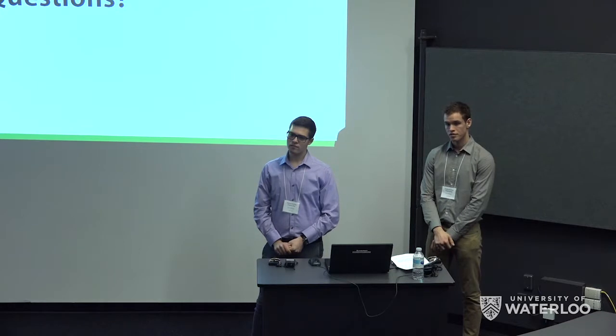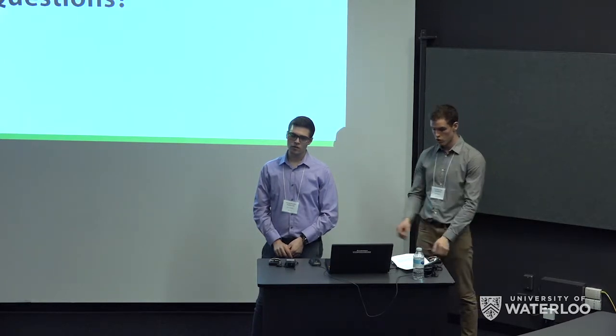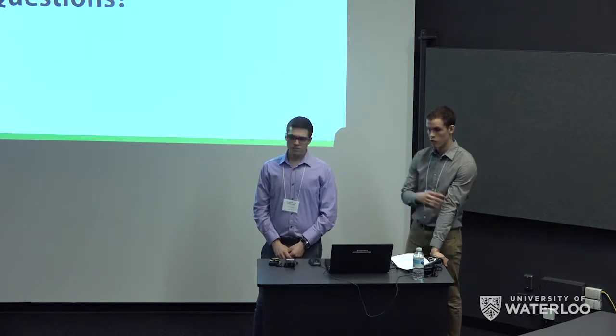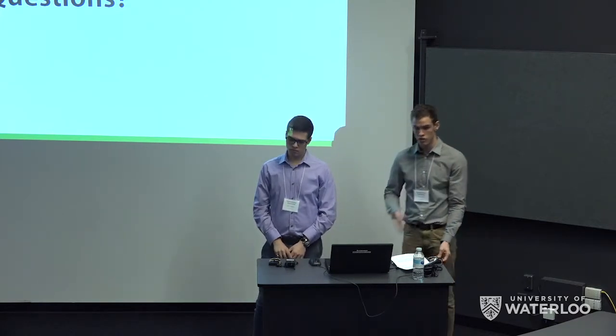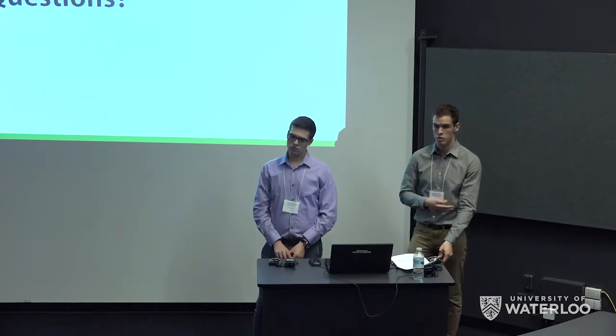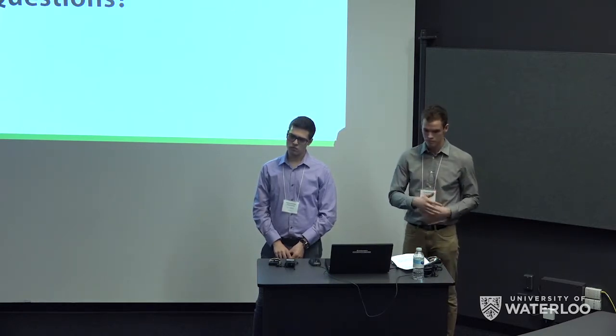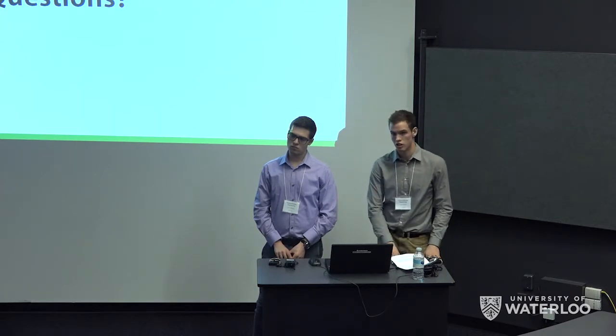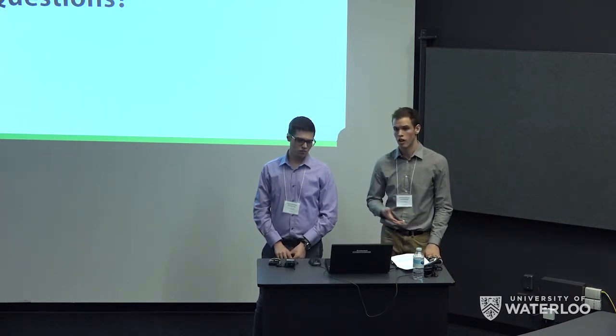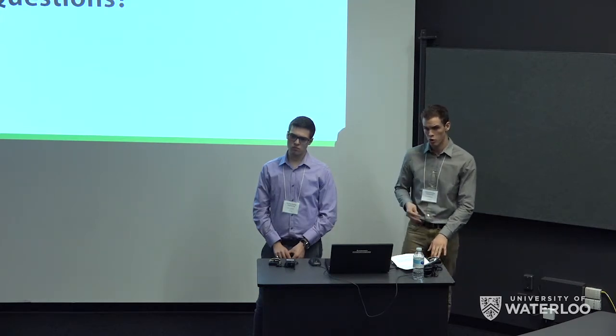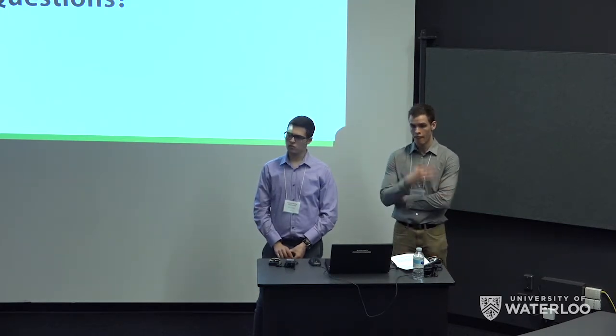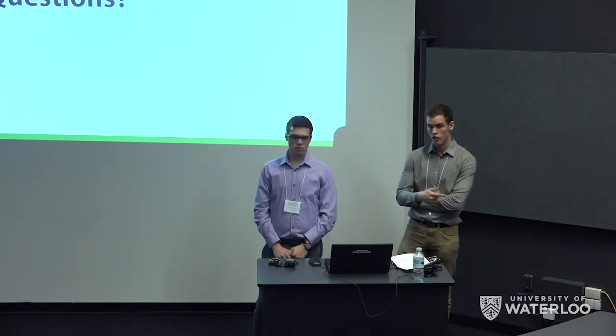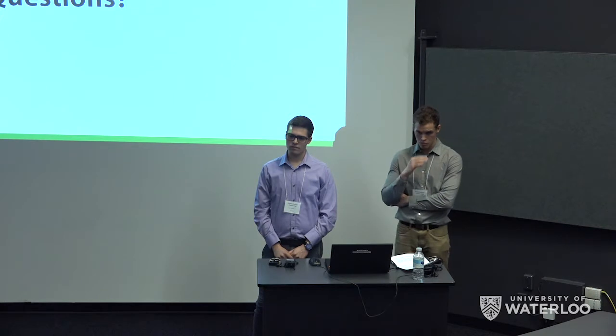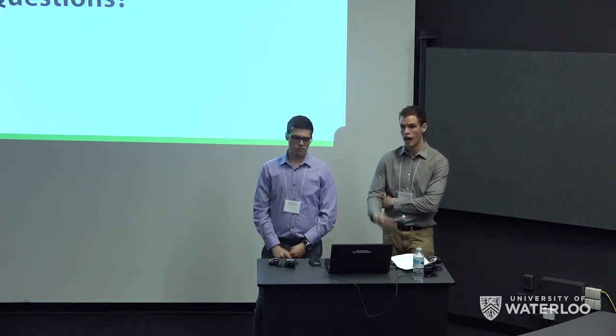So you said you use industry formulations. How much of the choice of filler and polymer is there? Is that their idea, and how much of it is your idea? So filler and polymer, essentially we were talking to Dr. Simone about this, and we suggested 5% and 10%, whereas from his experience using Ecosphere as a loading content, he suggested that a higher loading is generally more beneficial. None of our industry contacts actually recommended us any filler content. It was more based off of Dr. Simone's experience, 10 and 20 are good. And from my experience working with glass-filled polymers, you usually hit 50 or 30%. So edging towards higher is generally better.